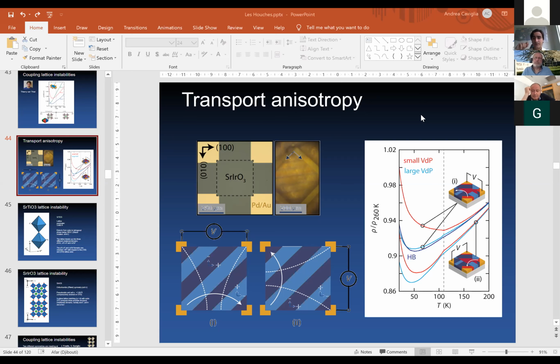I see. So you're not observing strictly the tetragonal domains of STO, but you're observing the domains of your layer, but they're just locked to one another. Yeah, exactly. So we are observing the action of these tetragonal domains on top of the structural domains of our layer. And if you would have done a SQUID, do you imagine also having modulated currents on the domain walls? So Beena Kalisky has these samples, and hopefully I'll be able to show you some.